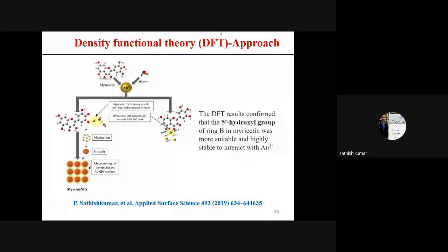So they found that the 5' hydroxyl group of the myricetin is involved in the reduction, as well as the carbonyl group of the myricetin, which interacts with the gold ions and is involved in the functionalization process. We have experimentally proved the functionalization process, but here they have used density functional theory.